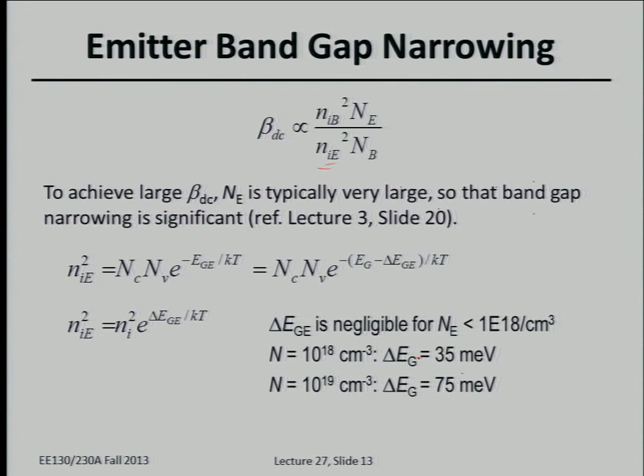Actually, the most commonly used high-performance BJTs today are heterojunction BJTs. So let me explain why this is the case. We'd like to dope the emitter much more heavily than the base, and the base has to be doped more heavily than the collector to minimize the base width modulation effect. So that means the emitter has to be doped pretty heavily. But if we dope the emitter very heavily, then there's going to be band gap narrowing, and so that's going to increase the intrinsic carrier concentration in the emitter. And that's actually counterproductive to gain, right?